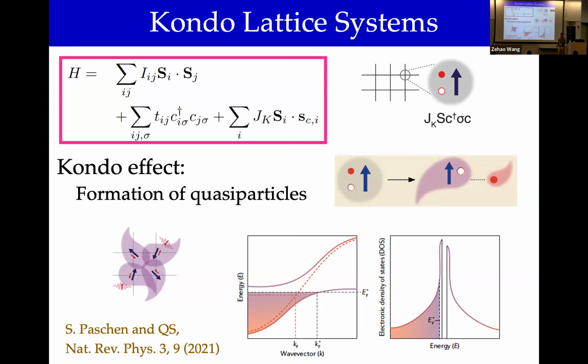The weight is the energy scale, that's the Kondo scale, divided by the bare conduction electron energy scale. The Kondo scale typically turns out to be on the order of several milli-electron volts. The bare electron energy scale is several electron volts. So the ratio is about 10 to the minus 3. And so this Z being 10 to the minus 3 manifests in a number of ways in